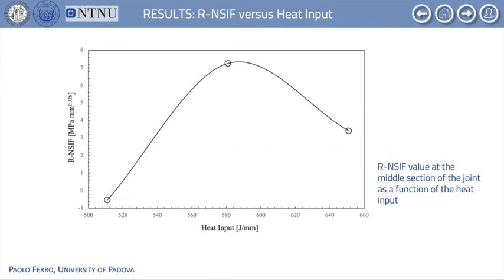This plot shows the residual notch stress intensity factor value calculated at the middle section of the specimen as a function of the heat input. It is interesting to note that an unexpected non-monotonic trend was found, which can be justified by a strong interaction between geometry, weld bead size variation, and the thermometallurgical history the joint undergoes for each different welding process combination. This interaction, here only captured by numerical simulation, will surely be a matter of future and interesting research work.